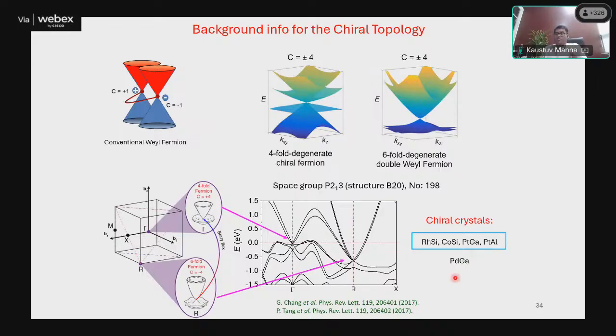As a consequence, the compounds which are predicted, a series of compounds, rhodium silicide, cobalt silicide, platinum gallium, are all, as you can see, diamagnetic materials, like a non-magnetic category of compounds. At the gamma point, it is seen that there is a four-fold degenerate crossing, whereas at the R point you have a six-fold degenerate band crossing. However, the most important part here is the Chern number, the topological invariant which I was discussing from the beginning slide, that is plus or minus 4, 4 times larger than in any other topological materials.